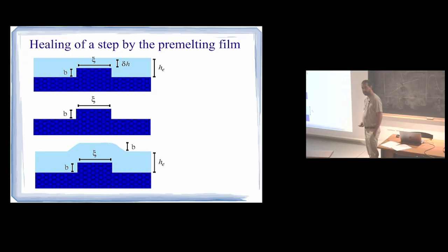You could have this other alternative. In wetting physics, these two alternatives are well known. This is called a healed surface. It has some bump, and the premelting film, the liquid film on top of it, has healed the bump. This is an important concept in painting. You want paints to heal your imperfections on the surface. This is the situation where the liquid film is actually obeying the dictates of the bump. So this is the healed state, and this is the, what's the state? I don't remember the name now, but it's the one in which the film follows the pattern.